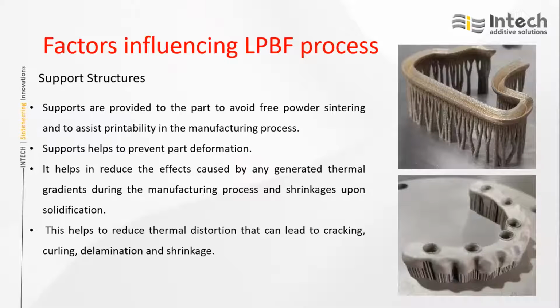Regarding support structures - if they are too strong, there is a difficulty in removing the supports. Supports need to be removed easily, and should not be too weak such that during printing we get a problem with delamination. So sufficient amount of supports and parameters need to be selected in such a way that it has sufficient strength to support the actual component. This will help reduce the thermal distortion that leads to cracking, curling, delamination, and shrinkage.